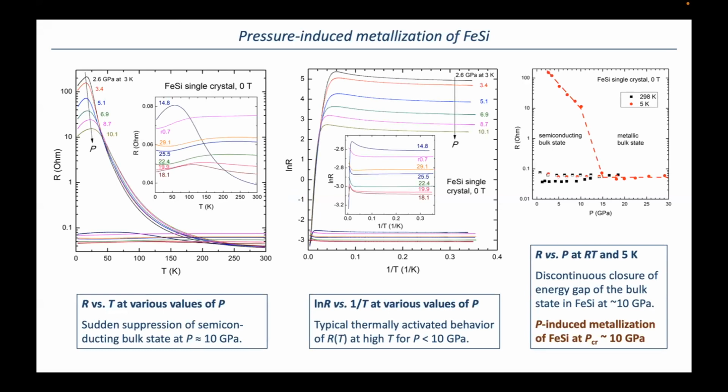These are measurements under pressure, which are also quite interesting. This is not published. The previous work was published recently. Here's resistance versus temperature, and you can see that the resistance decreases, and you have evidence again for the conducting surface state with this peak. This decreases and then abruptly decreases into what appears to be a metallic region, and that's shown in more detail here.